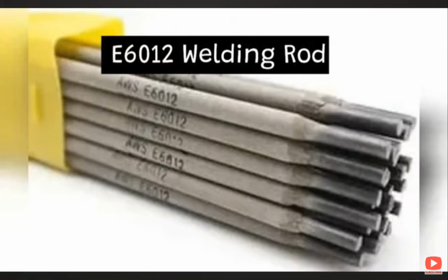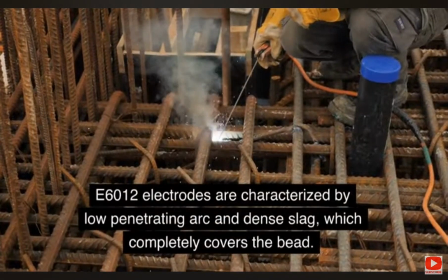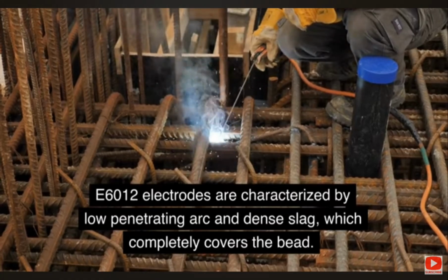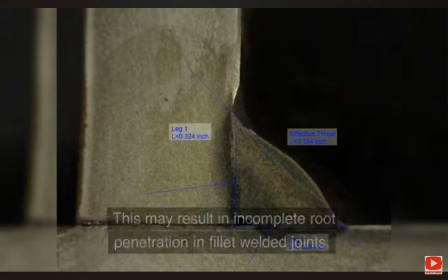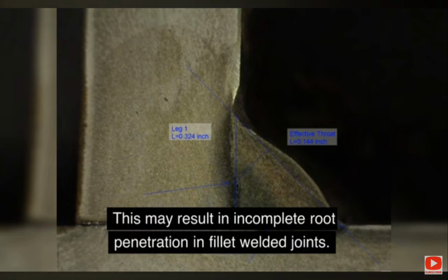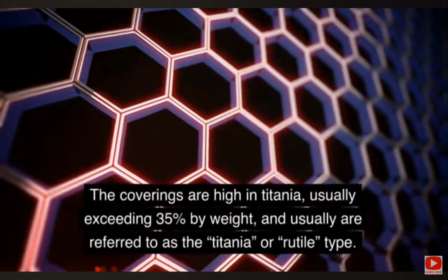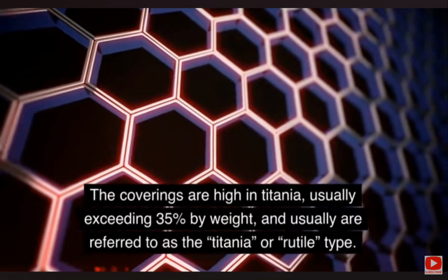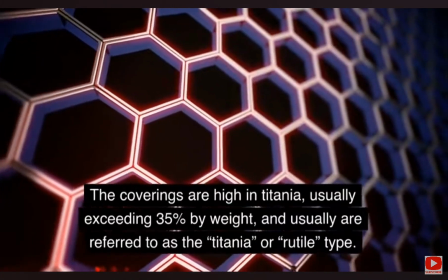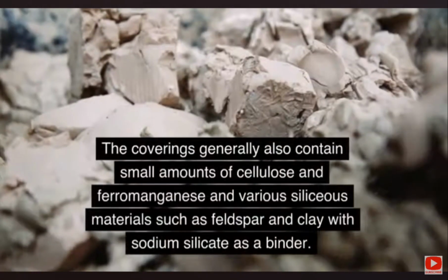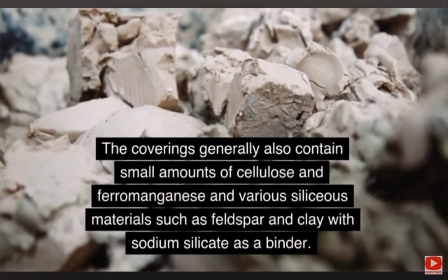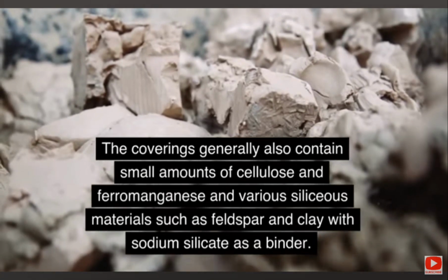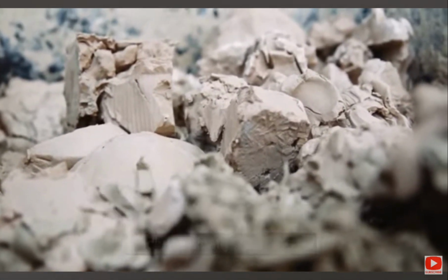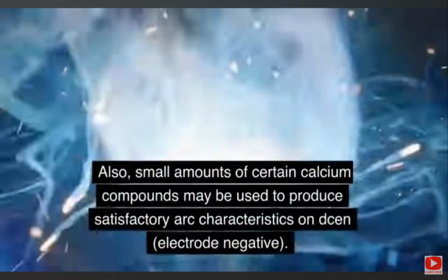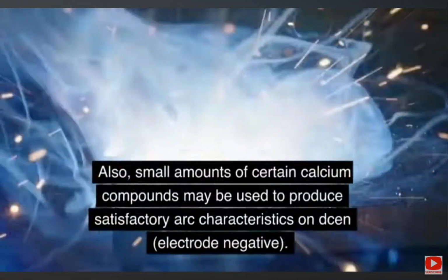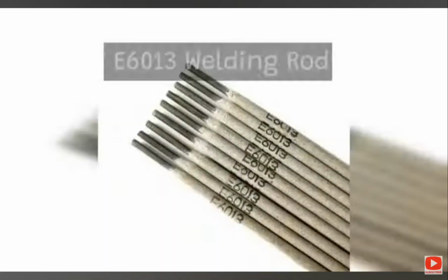present. E6012 welding rod. E6012 electrodes are characterized by a low penetrating arc and dense slag, which completely covers the bead. This may result in incomplete root penetration in fillet welded joints. The coverings are high in titania, usually exceeding 35% by weight, and usually are referred to as the titania or rutile type. The coverings generally also contain small amounts of cellulose and ferromanganese and various siliceous materials such as feldspar and clay with sodium silicate as a binder. Also, small amounts of certain calcium compounds may be used to produce satisfactory arc characteristics on DCEN, electrode negative.